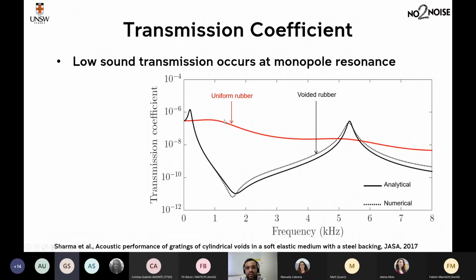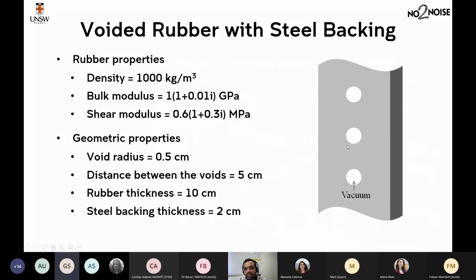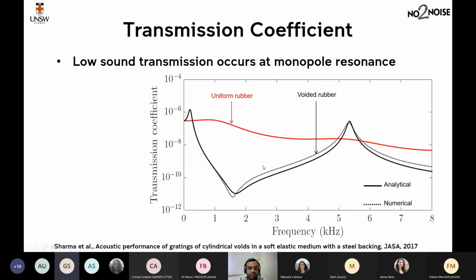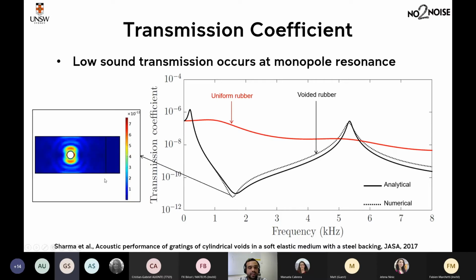On this slide, I am comparing the transmission coefficient of a uniform rubber. When I say uniform rubber, it just means that we have a rubber medium like this, but no cavities, right? And that rubber medium is attached to your steel backing. You can see that when you have cavities in your rubber medium, the transmission coefficient can be reduced significantly, especially around the monopole resonance frequency. And again, this figure shows the displacement or deformation of the soft medium. Again, I'm just showing a unit cell. You actually have a repetition of this in this direction. So again, here the monopole resonance of voids leads to low sound transmission.